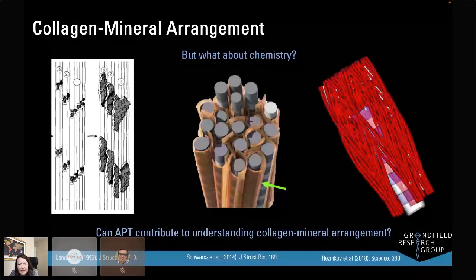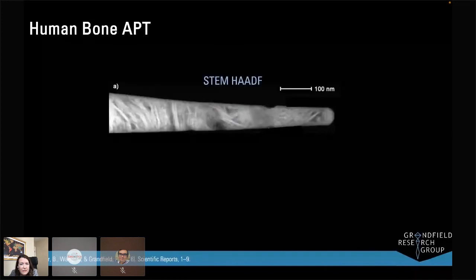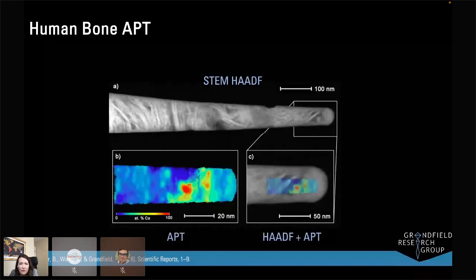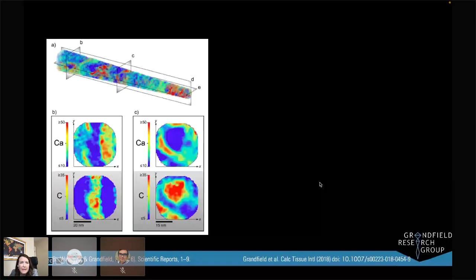So we prepared samples of human bone and looked at this. This is an example of what it looks like inside the microscope, and we place this sample in the atom probe microscope, evaporate those atoms as I described previously, and create a three-dimensional map. We're able to have good correlation between our images and our 3D chemical data, and when we look at that over a larger scale, we see an example here from the atom probe microscope.